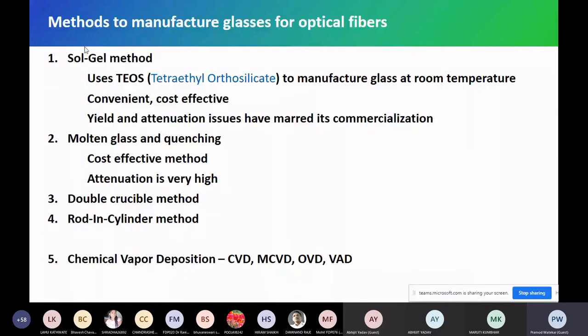I worked in the sol gel method. Those among the audience who have worked on sol gel know it's very easy to make. You take TEOS, put water, and add whatever contents you need, leave it overnight, and you get the liquefied glass. Then you put it for drying for 1 week, and we get the glass. It's very easy to make. The problem is that it's very difficult to get the yield. There are so many cracks. You have to control those cracks.